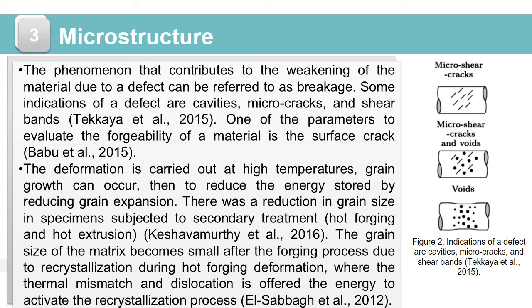If deformation is carried out at high temperature, grain growth can occur, in order to reduce the stored energy by reducing grain boundaries. In the research conducted by Ozer, it was found that there was a reduction in grain size in specimens subjected to secondary treatment.